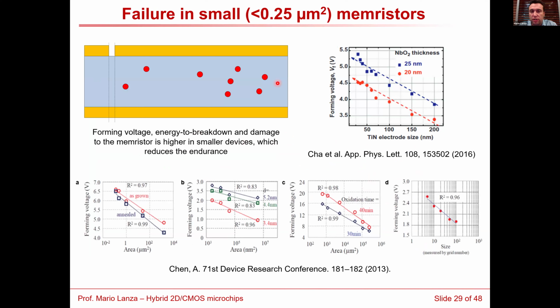If you have a resistive switching material, this material has a random distribution of defects. When you have a very big device, you have a high probability of catching defects. And for the small device, you have a low probability of catching defects, okay? The key is that in our devices, the resistive switching is based on the filament, and the filament is formed in the locations where there are defects. If you have defects, you are triggering the breakdown at low electrical field and forming one small filament that can be easily reverted. But in the small device without defects, look what happened.